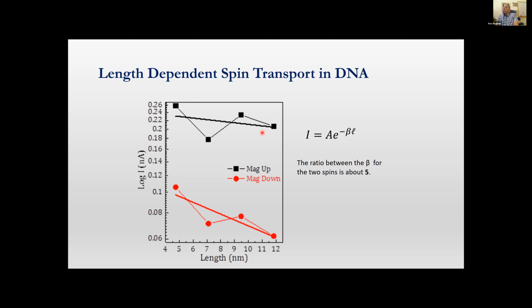We have to remember that in this model, the spin is coupled to the linear momentum. Therefore, backscattering means that the electron has to switch spin in order to be scattered back. So if the electron has the preferred spin, it will go with very little backscattering. However, if the spin is not preferred, the backscattering will be very efficient. That's very similar to the effect observed in topological insulators.